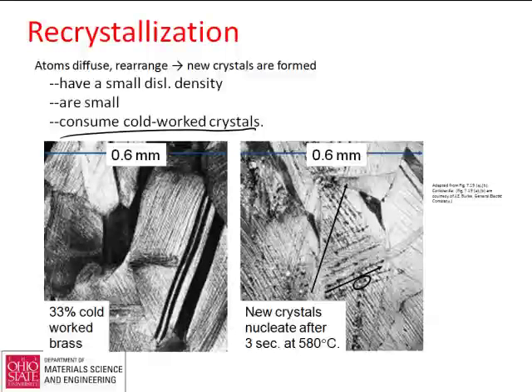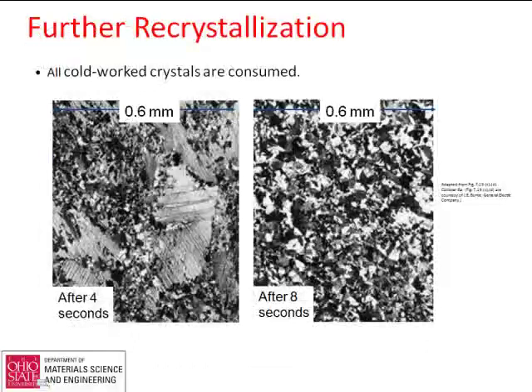So new crystals nucleate after just 3 seconds at 580 degrees C, and this is for a brass, I believe. Yep, 33% cold work brass. And give it a little more time. After 4 seconds, you're seeing bigger crystals. After 8 seconds, a lot of them, and that's at a reasonably high temperature. But again, what it's showing is with the same composition, just by adding some temperature to it, we can cause the structure to change. That change in structure changes the strength pretty significantly. And that's the core idea that I think you could do in ninth grade.